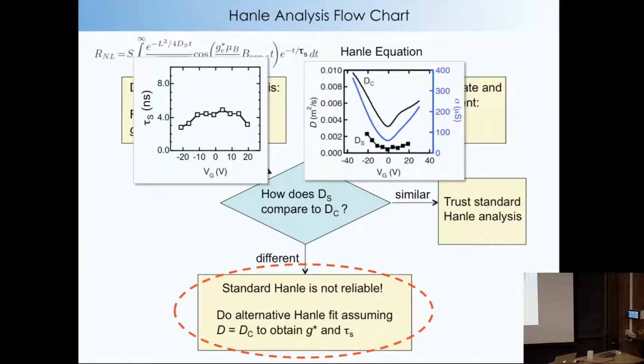What does that assumption amount to? Assuming D equals DC. Well, I think it's a good assumption, but there's some error bars. Where the error bars come in is that to get the DC, you have to assume a certain amount of broadening for the density of states. You don't have to do that for bilayer, but for single layer, you have to do that. And so this shape could change a bit. The DC can change a bit because of that. So that, I think, introduces the biggest uncertainty.